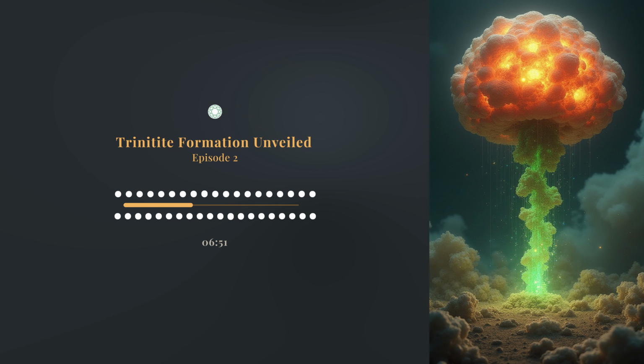Generally, yes, and their shape is also a clue. Often, especially near the top, the bubbles are elongated, kind of stretched out parallel to the original ground surface. What does that mean? That elongation strongly suggests very rapid cooling, quenching of that top surface, stretching the bubbles as the glass solidified. The material underneath may be insulated a bit, likely stayed hotter for slightly longer. Allowing more gas to come out and form those denser, smaller bubbles. That's the interpretation, yeah. Prolonged heating below. It's also noted that areas rich in potassium, probably from melted K-feldspar, often have more bubbles. Perhaps those grains degassed more as they melted. So even the tiny bubbles are like little records of the heat flow and mineral reactions. Yeah, exactly. It's like reading a very fast, very violent geological event in micro detail.